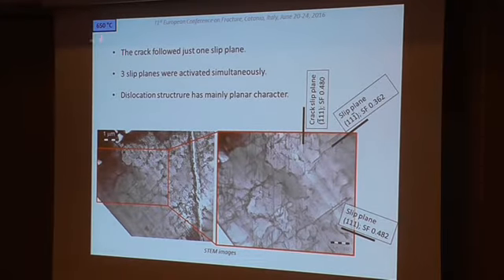At this temperature, 650, where we observed mostly the crystallographic crack mode, we can say that the dislocation structure is mainly planar, crystallographically dependent, and in some grains, or maybe in most of the grains, numerous slip planes are activated, and the crack follows just one of them.